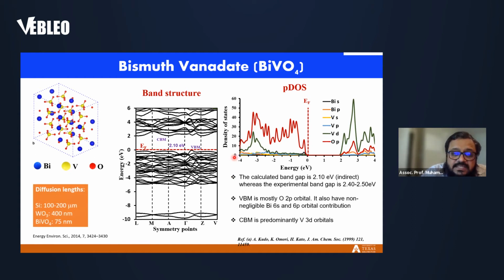And then I would like to present the electronic structure of pristine bismuth vanadate. Two points to note here. One, the band gap. The calculated band gap is 2.10 electron volt, whereas the experimental gap is between 2.4 to 2.50 electron volt. So there is an underestimation of the band gap, which is typical for density functional theory. The second point I would like to note for polaron formation, we know that hole polarons usually form near the valence band, and the valence band of bismuth vanadate is dominated by oxygen p orbitals. So the hole polaron will likely form on the oxygen side. Similarly, the electron polaron will likely be formed on the vanadium side because the conduction band minimum is mostly from vanadium 3d orbitals.